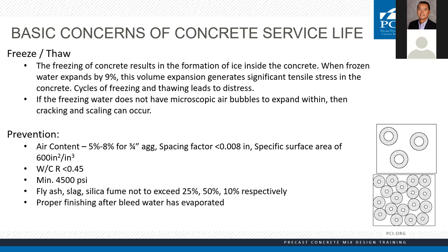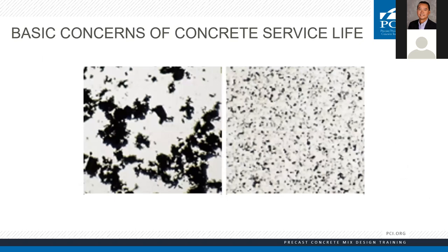Note this point on prevention of freeze-thaw damage: fly ash, slag, and silica fume should not exceed 25%, 50%, or 10% respectively. Up to this point for every durability factor, we've been saying to increase SCM use. But when freeze-thaw comes into play, there are limits on how much SCM we can use — very high SCM content may give us freeze-thaw issues. Here's an example of air void analysis: two samples both have roughly 5.5% air content. The sample on the left has large irregular bubbles with lots of unprotected concrete. The 5.5% air on the right has small evenly spaced bubbles that protect the entire surface.